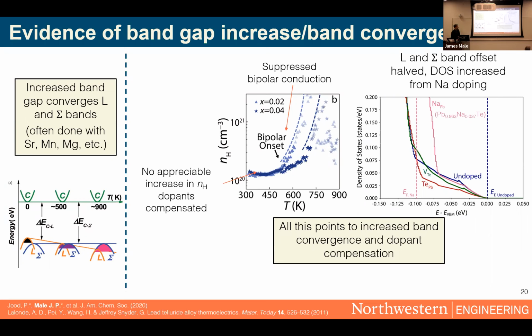In the past, there have been several strategies to expand this band gap, push the L band down in energy, and increase the convergence between these two bands, which improves thermoelectric performance. Typically this has been done with strontium, manganese, magnesium, and all of these non-doping alloying elements. What we found is that we have evidence this is happening from sodium doping at very high concentrations.